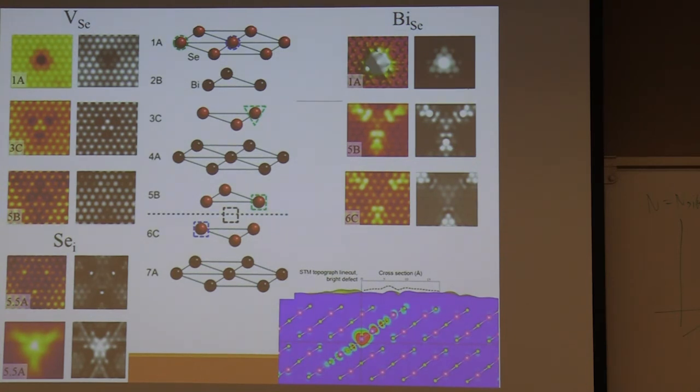So when you're at room temperature, you have more defects in your material than this would suggest. Typically, if you apply this to a real system, you think about what the growth temperature is, and you calculate the defects based on the growth temperature, but then they can get locked in when the system cools down. You can't just bring the system down to 4K and the defects are going to disappear. In order for them to disappear, there has to be some kinetic pathway where they have enough energy to go over the barriers to reach equilibrium. In principle, it would reach equilibrium eventually, but not on any reasonable, you know, universe time scale.